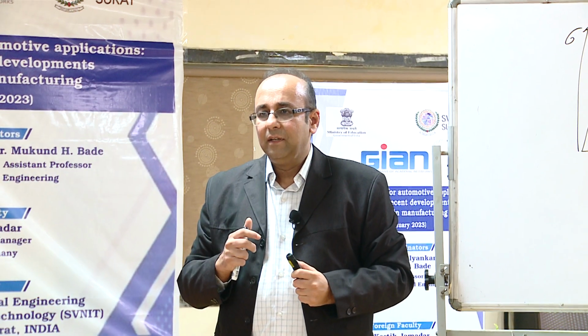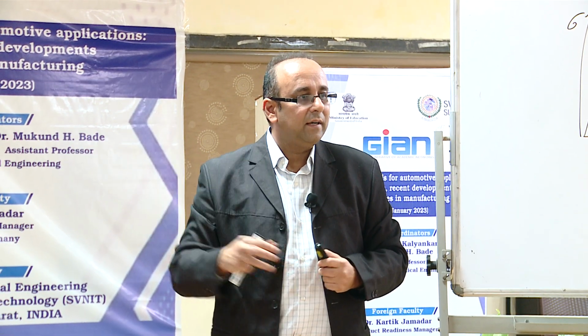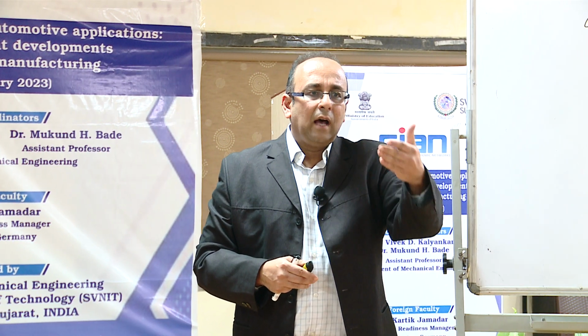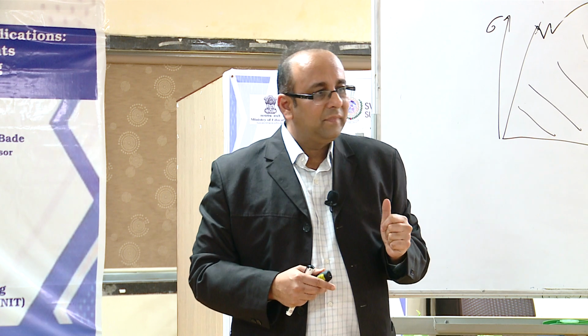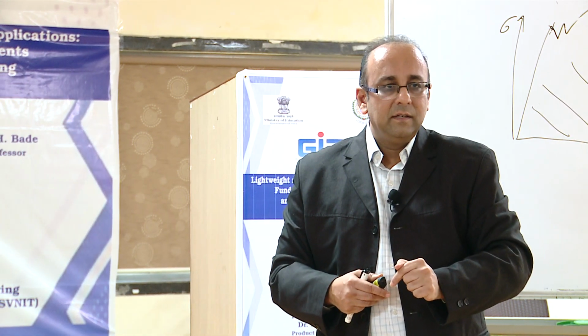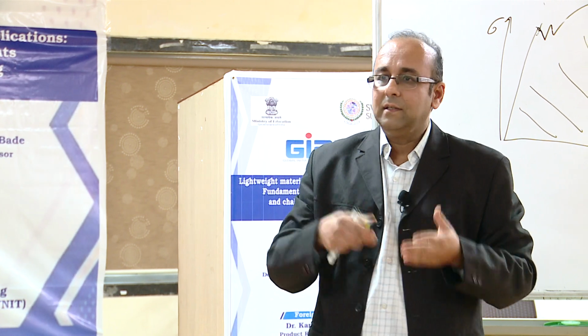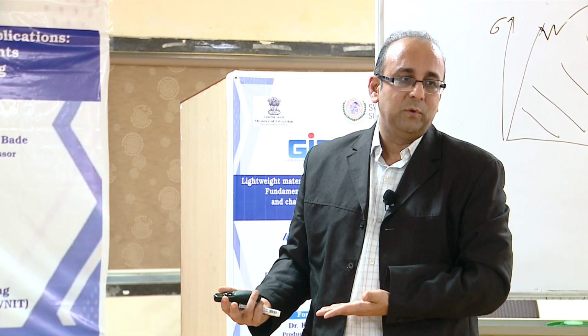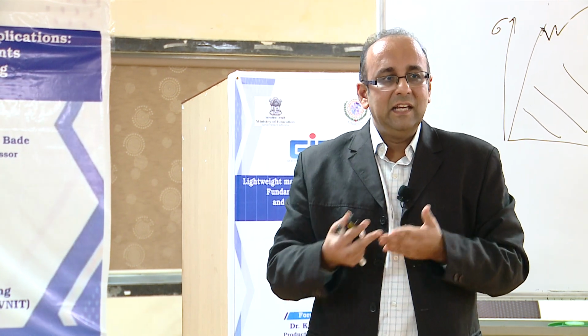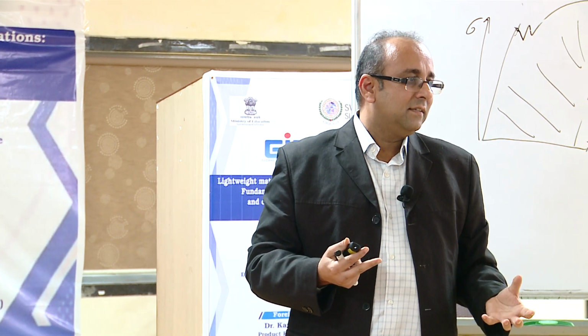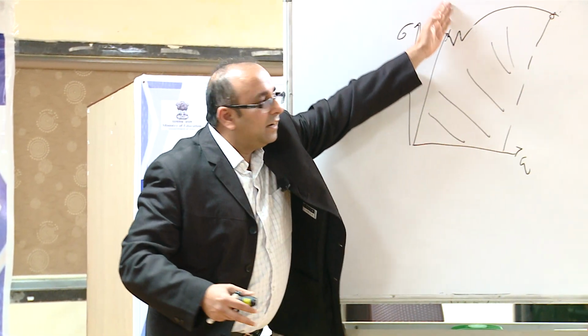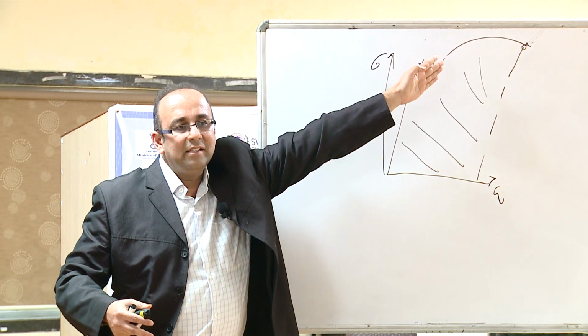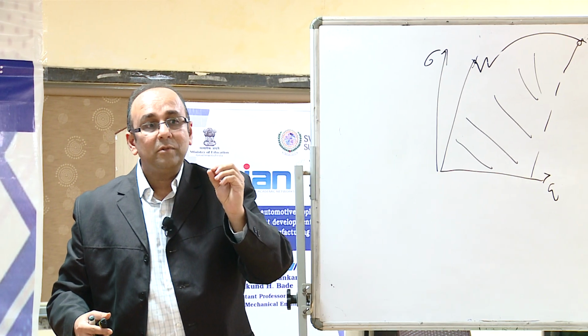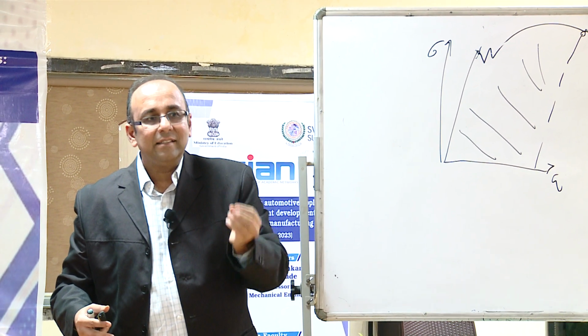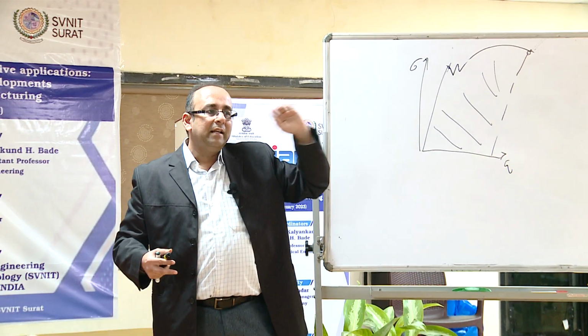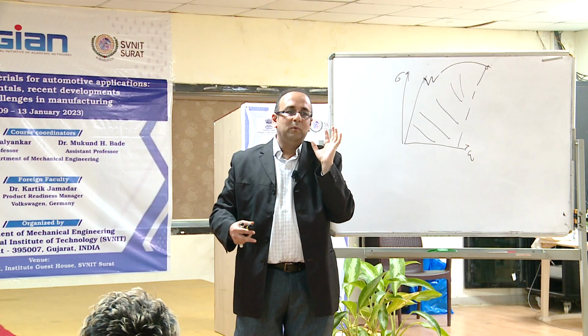So dual phase steel that we had studied, DP600, DP700, DP800, ferrite, martensite. Now people say, I don't only have ferrite and martensite. I also have bainite, pearlite, even carbides. Why not mix it? Yes, that's exactly complex phase material, CP material. It is basically pearlite in bainite with some retained austenite and some retained martensite. So now what we are doing is increasing again the strength, and basically your pearlite is giving you that deformation, plus you have some retained austenite. We don't want to convert that. That is again added by some silicon, manganese, and we are getting that formability. So CP materials, complex phase material.